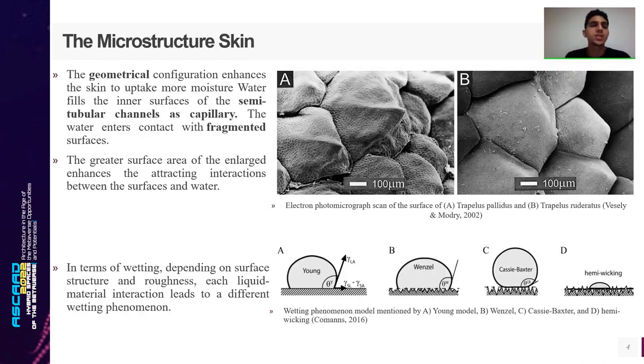When water comes into contact with fragmented surfaces, the geometrical configuration is very important to enhance the skin's uptake of more moisture. That's why water fills the inner surfaces of the semitubular channels as capillaries. The greater the surface area, the greater the interaction between the surface and water. In terms of wetting, as shown in this figure, depending on the surface structure and roughness, each liquid-material interaction leads to a different wetting phenomenon.